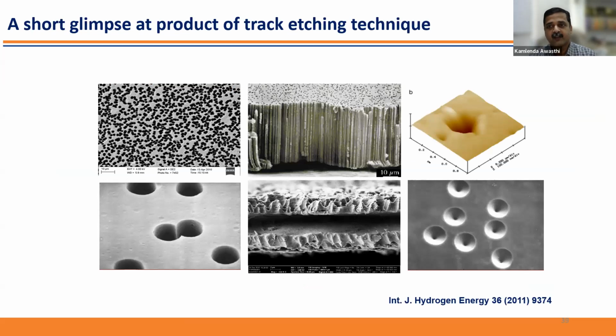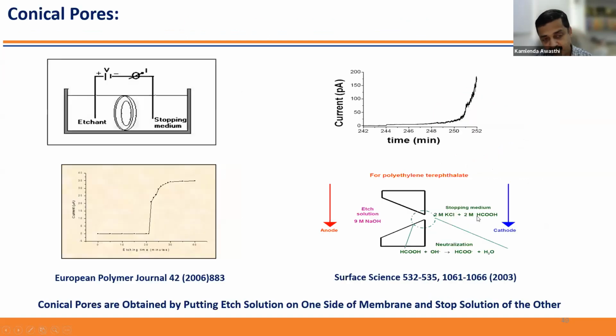And here you can see the SEM images, this is the top view. This is 10 to the power 8 ions per centimeter square. Here you can see some pores overlapping each other. And this is the cross-sectional view. You can see the pore is through and through, and this is the cross-sectional view for a single pore. You can see the porosity is the same throughout the polymer. And if you etch from one side, this is the cone-like structure in your polymer.